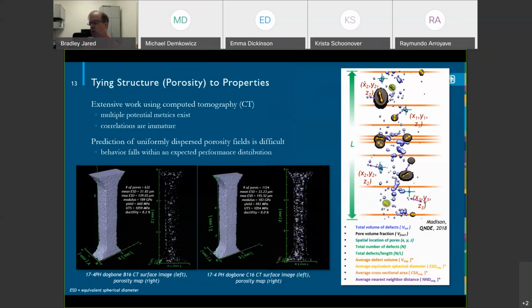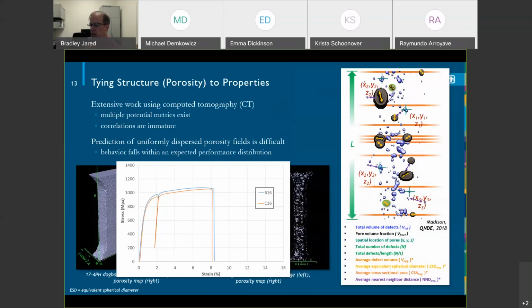We have two different dog bones, the left one and the right one, B and C, I guess it is. And we look at those porosity fields and we think the one on the right, C, is going to have a much lower strength and much lower strain to failure because there's a larger porosity field. It has a lot more defects in it. You would expect a large difference in the performance. But when you overlay the stress strain curves, they're right on top of each other, right? And so there's sort of two sides of this. One is encouraging in that you can say, well, okay, these defects matter, but how much do they matter? And maybe these materials can be more robust than we thought.